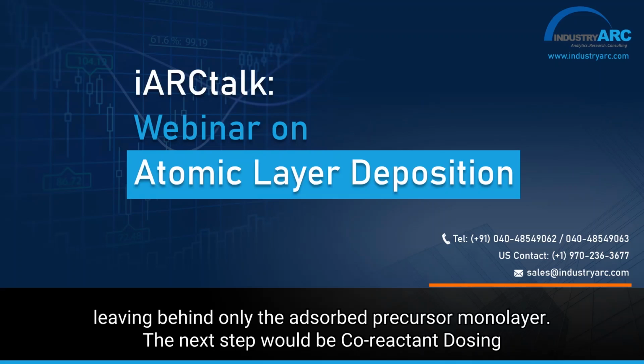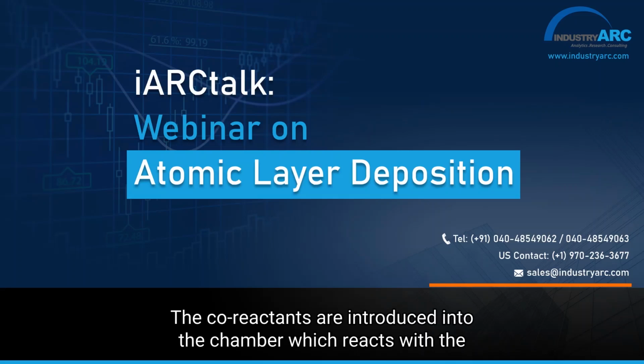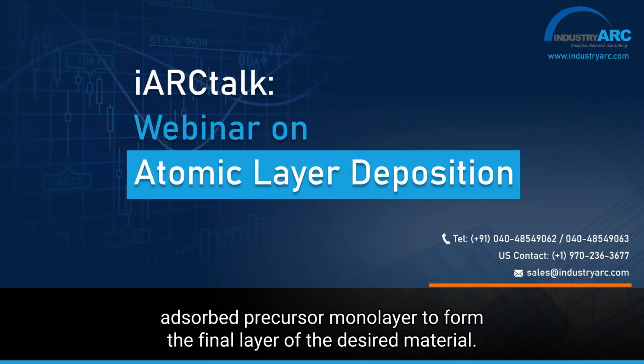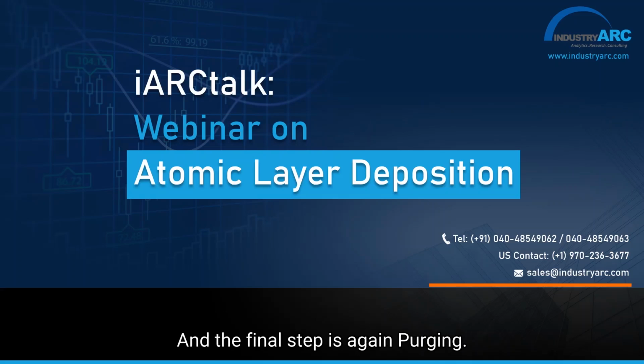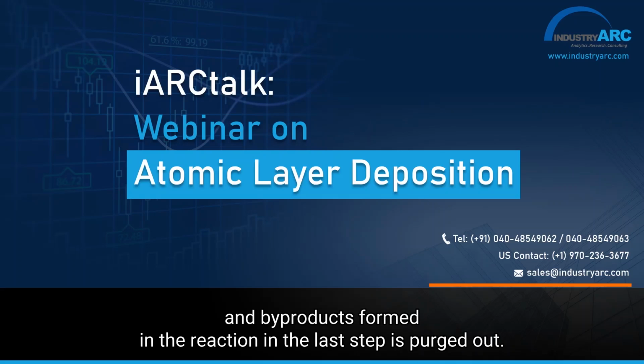The next step would be co-reactant dosing. The co-reactants are introduced into the chamber, which react with the adsorbed precursor monolayer to form the final layer of the desired material. And the final step is again purging. The unreacted co-reactant molecules and byproducts formed in the reaction in the last step are purged out.